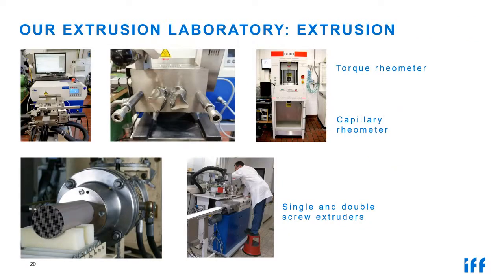Okay, now we have received the paste, and what are we now doing with the paste? The first is not to make an extrusion test, but first to test the properties of this material. For that, please have a look at the two pictures left above. In the first line, we are using a torque rheometer from Brabender, which is nothing else than a small kneading chamber with two kneading paddles, which you can see in the middle picture. In this kneading chamber there is a torque sensor, and this torque sensor indicates very precisely where the gelation starts, because at the point of gelation of the cellulose ether in the ceramic paste, your torque will rise up. In an extrusion test, your pressure would rise up.